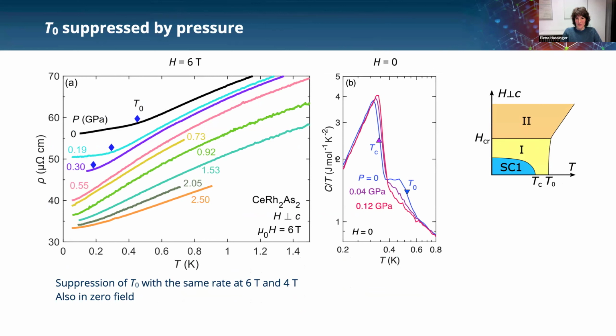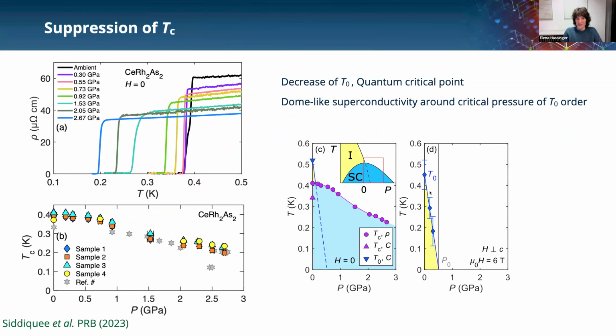And this is confirmed by specific heat measurements shown here as a function of temperature, where we have this nice T0 anomaly at zero pressure, and then it's strongly suppressed at very small pressures of 0.1 GPa. So now please look here first on the right. We have this T0 suppression with pressure that you see here, and there seems to be a quantum critical point